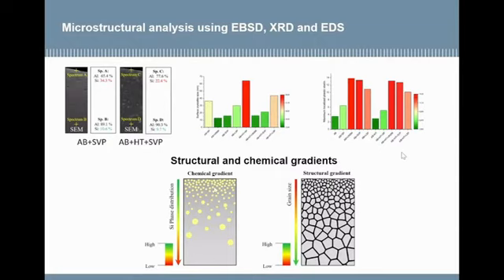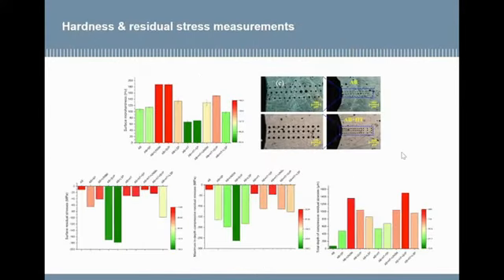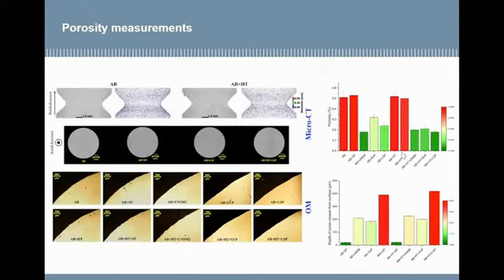And also in terms of the chemical gradient, we have the density and size of the Si particles that are closer to the surface as we go towards the core material. And these results were affecting the distribution of the hardness and also residual stresses depending on the kinetic energy of the treatment. Here I'm showing just the main parameters in terms of surface microhardness, in terms of surface residual stresses, depth of residual stress, and maximum residual stresses that were changing depending on the treatment that was applied on our material.